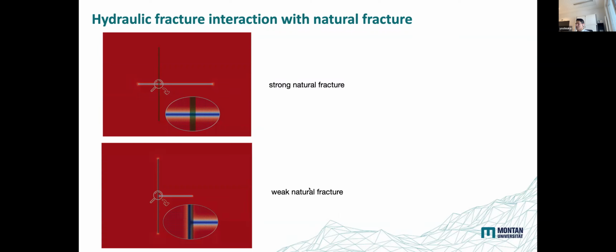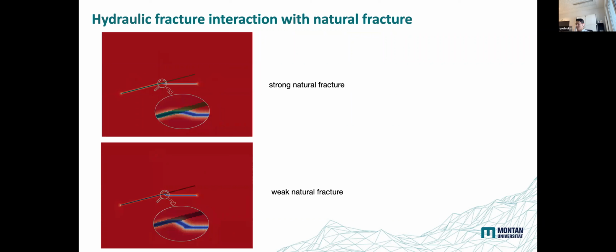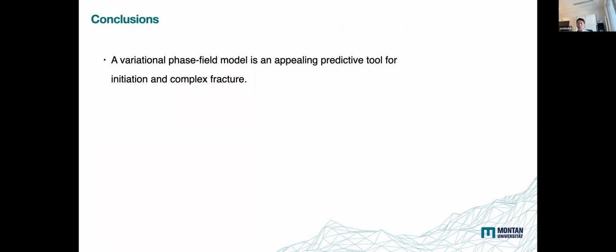And when we reduce the strength of this natural fracture, it branched on this natural fracture. So it split into two ways, and then it followed this natural fracture. And when we change the angle, so the fracture approaching angle is smaller in this case, with two different strengths of the natural fractures, strong and weak, in both cases the hydraulic fracture propagated along this natural fracture. Okay, so that's all I have for examples.